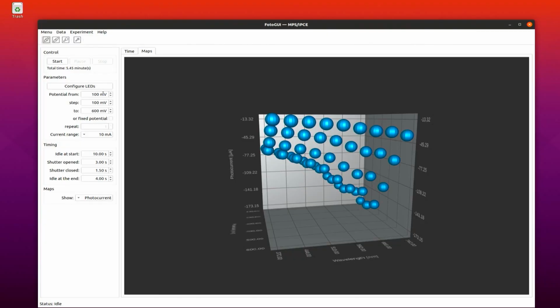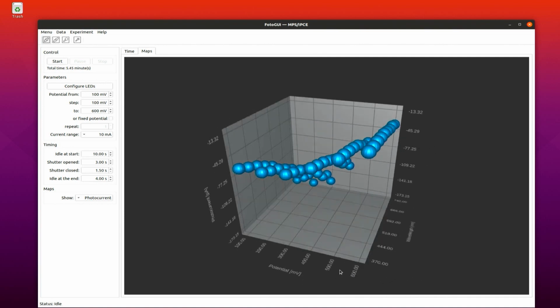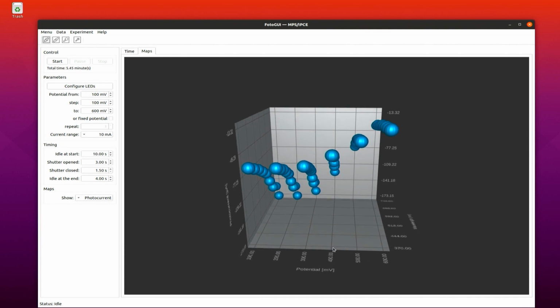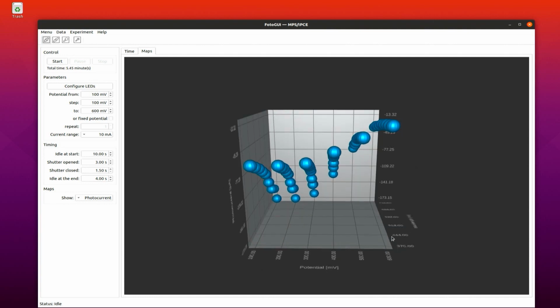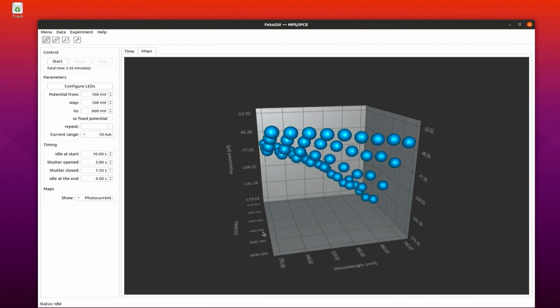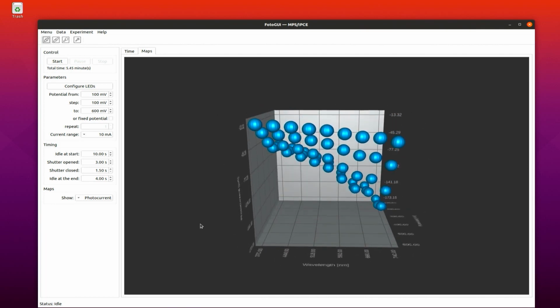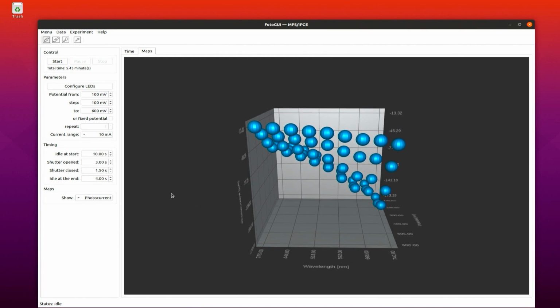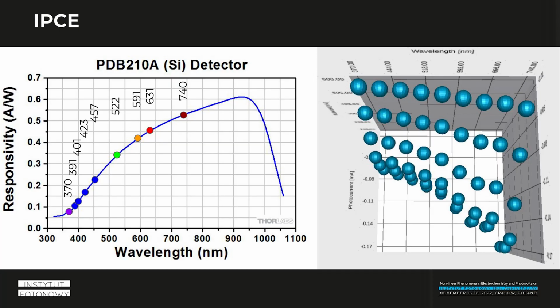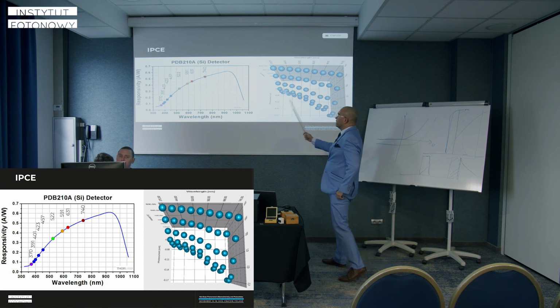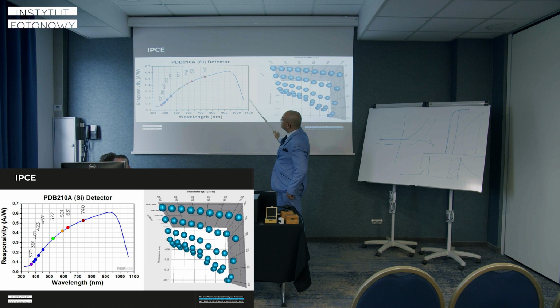We apply potential from, in this case, for example, 100 millivolts with a step of 100 millivolts up to 600 millivolts. So on this axis we apply potential with steps of 100 millivolts, and along this axis we have wavelengths. And this is a silicon photodiode. Let's switch to the presentation again. And look, our dots are not equally spaced, and this is just any silicon photodiode sensitivity curve. The silicon photodiode sensitivity maximum is in the infrared range.